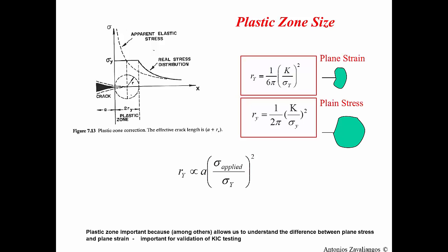Now that we have a good idea about the stresses in the area around the crack tip, we can start understanding the area and estimating the area where plastic deformation occurs. And the simplest approximation to it is actually to take the value of sigma yy, that is the vertical stress, and go back to the formulas that we had looked at a few slides ago.